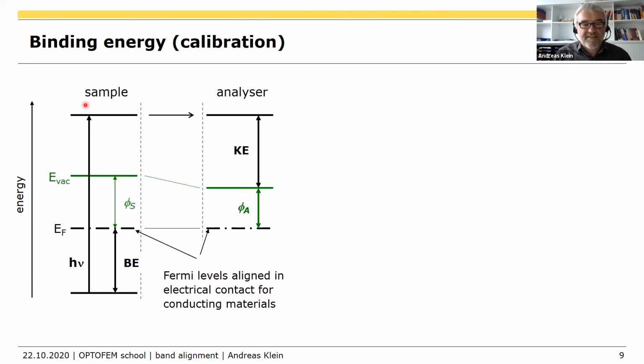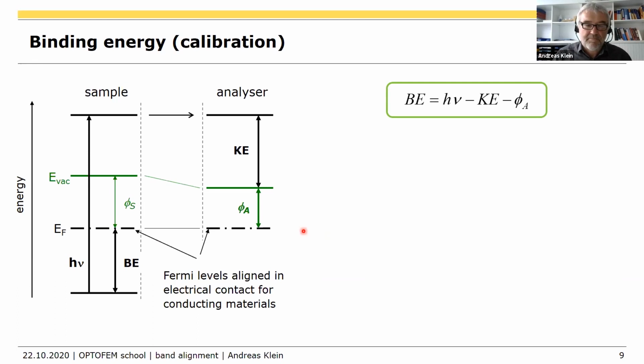And the analyzer and the sample are in electrical contact. And that means their Fermi levels are aligned. Even if they are not physically in contact to each other, the Fermi levels are aligned through the cable between the manipulator and the analyzer system. Okay, and that means the Fermi levels are aligned. This is in equilibrium. So now you can get the binding energy.